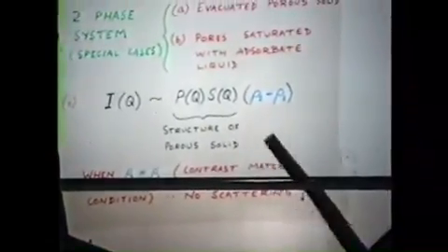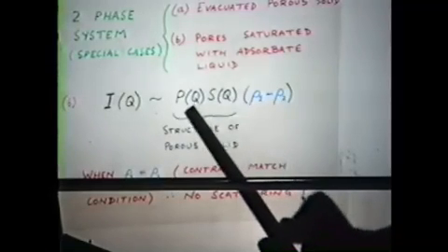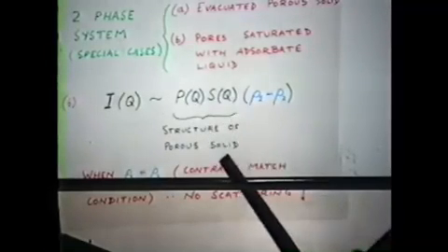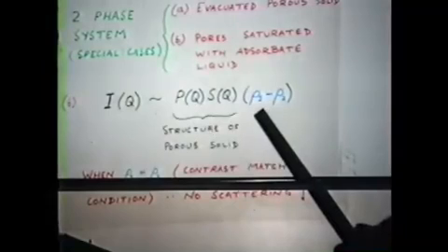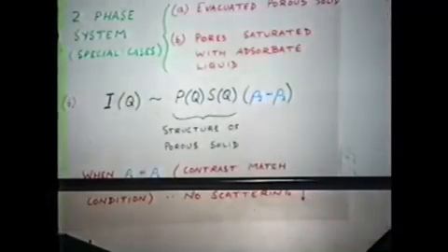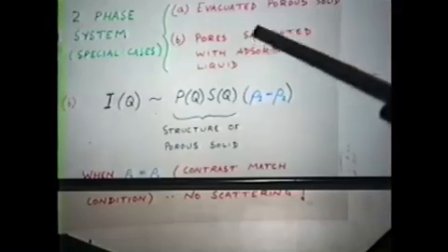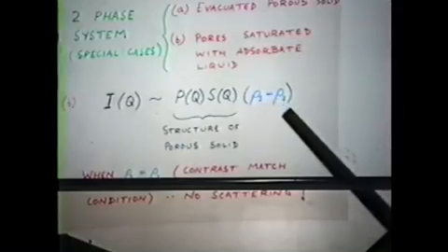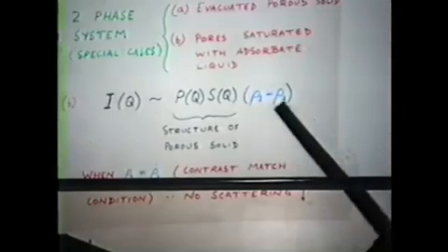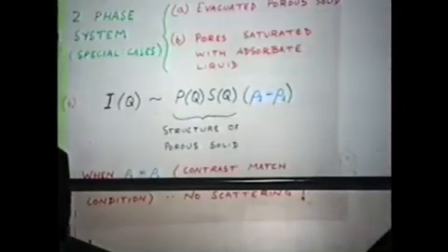And in that particular case, the intensity of scattering, I won't go into the details, is given in terms of these factors here, which relate to the structure of the porous solid, and two terms which are related to the scattering length density of these two phases. So in this particular case, it would be the solid and the liquid filling the pores.